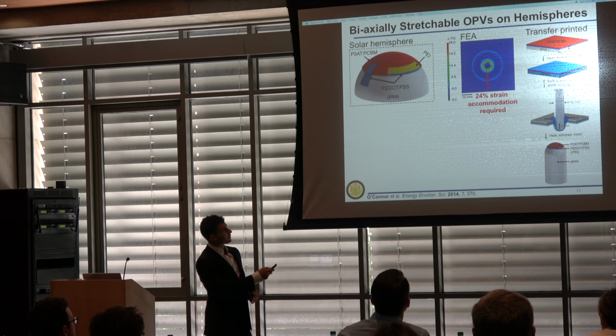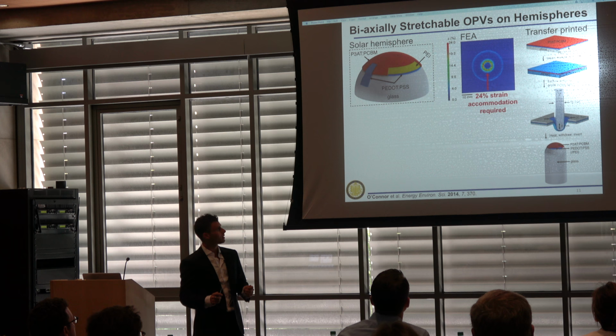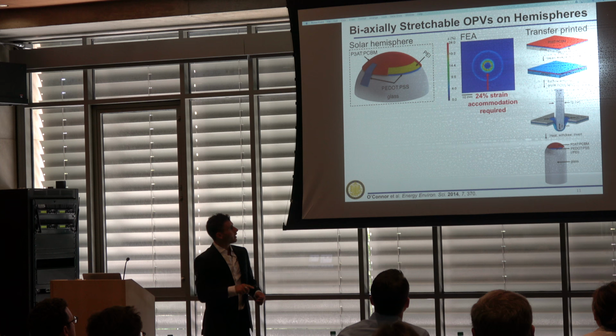This is our transfer printing process. We would actually build our solar cells first on a PDMS sheet, an elastomeric substrate, and then drive a test tube into it in a controlled fashion with a linear actuator. Heat it, release, and this would transfer print the solar cell. And just to get more quantitative,